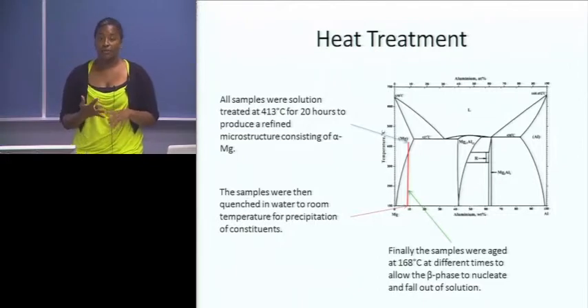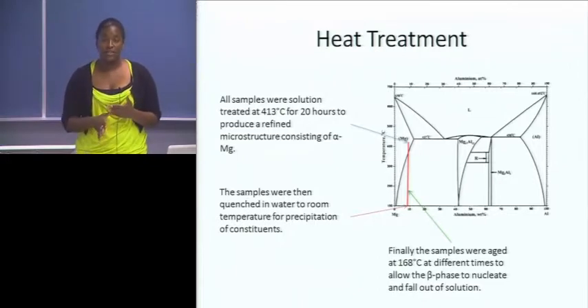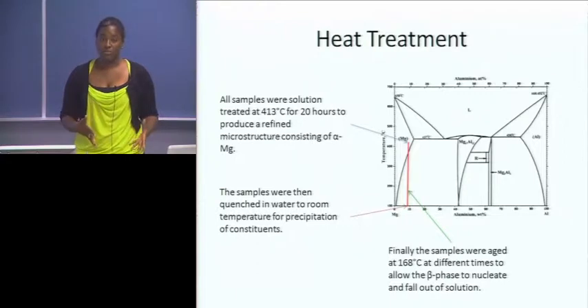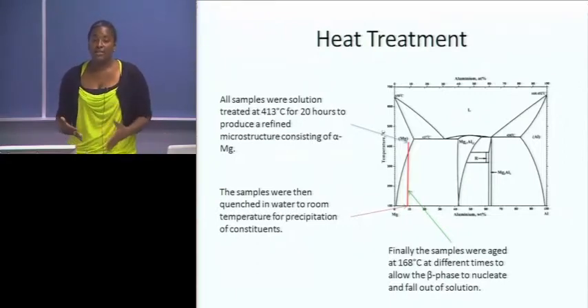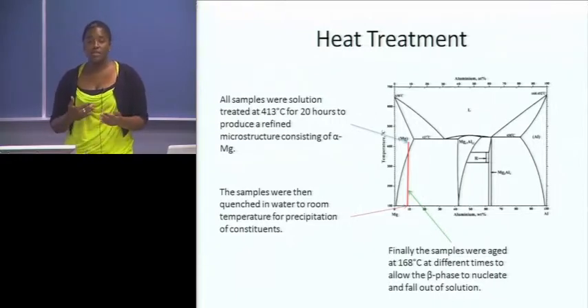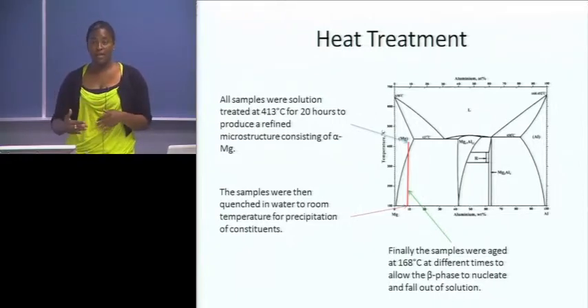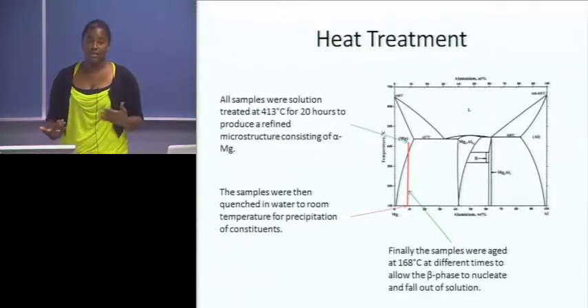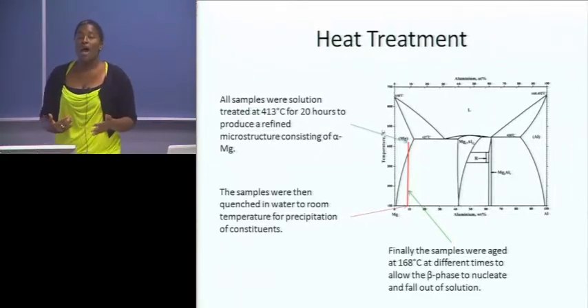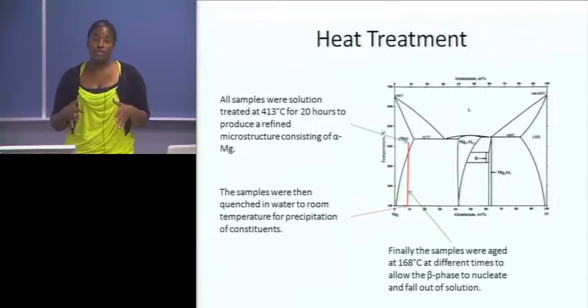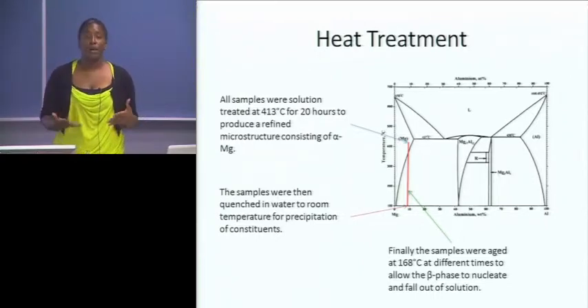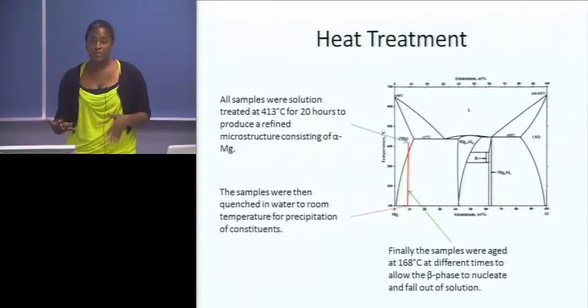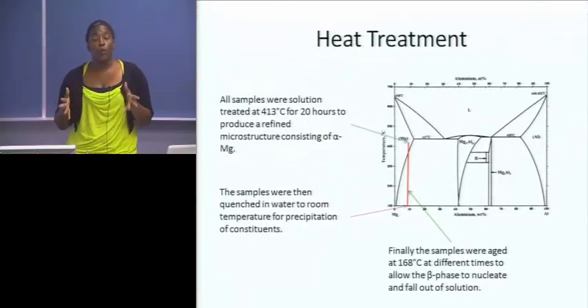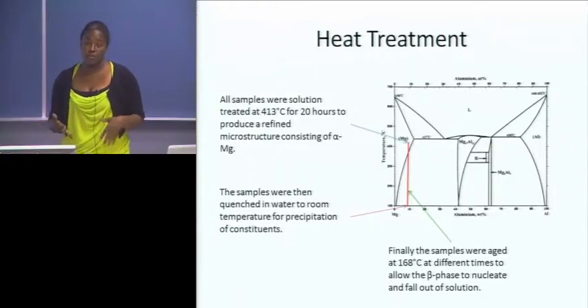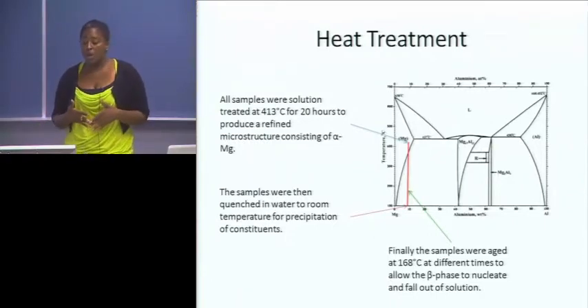I aged at 1 hour, 3 hour, 5 hour, 10 hour, and 50 hours to see how that changed the precipitation microstructure. So the precipitates in the AZ91 alloy grow either discontinuously or continuously. Discontinuous growth is alternating plates of alpha magnesium and the beta phase, and the beta phase is magnesium 17, aluminum 12. And usually they grow along the grain boundaries and they're large, they're easy to see even in optical microscopy. And then the continuous precipitates are much smaller and they grow within the grains, and they are also the magnesium 17, aluminum 12